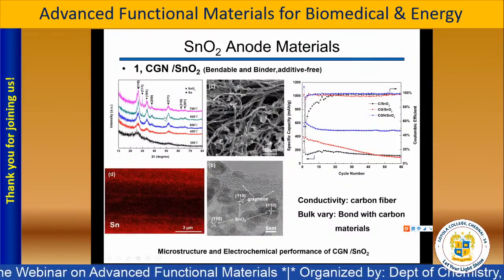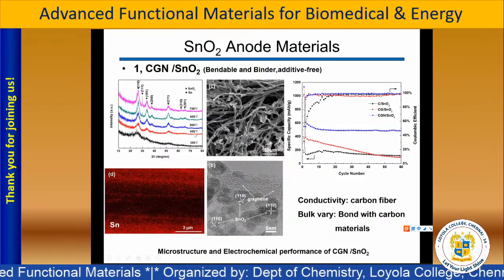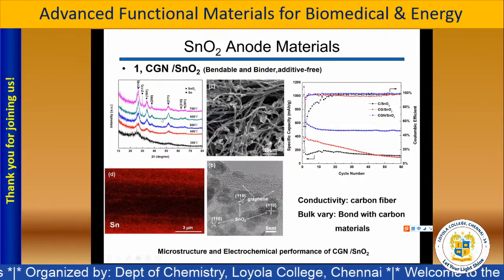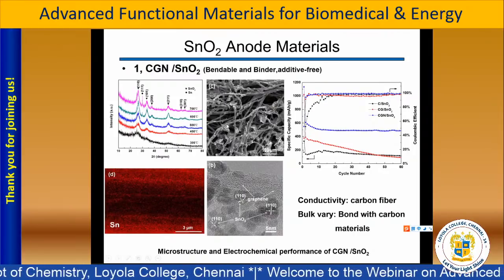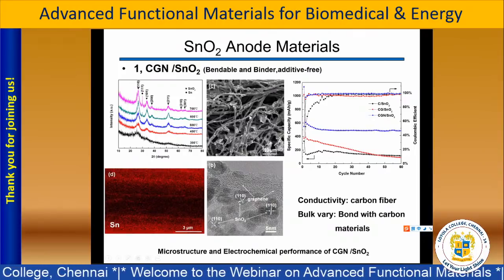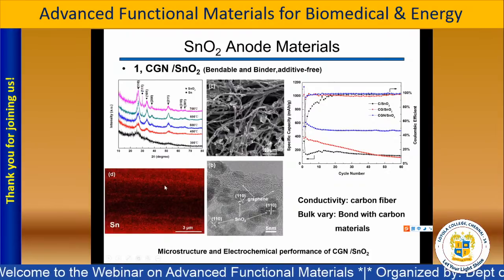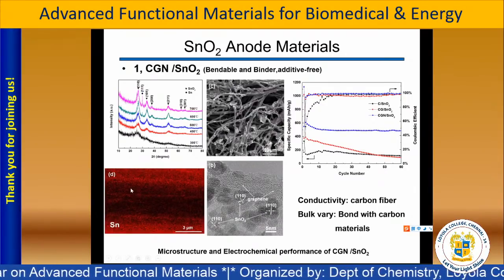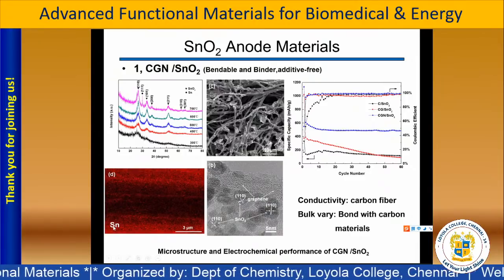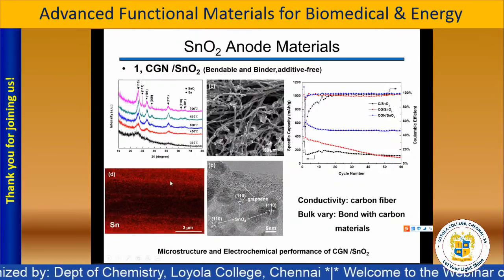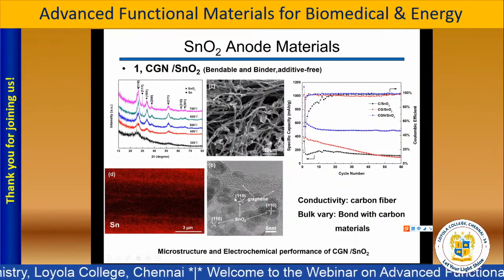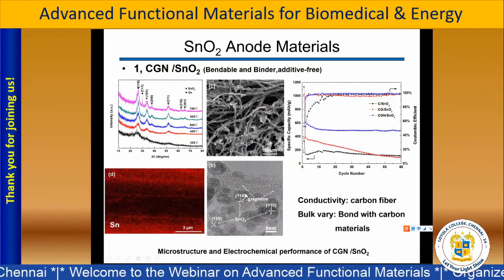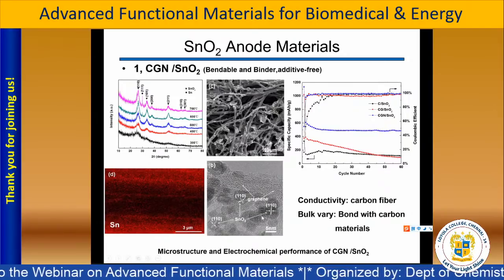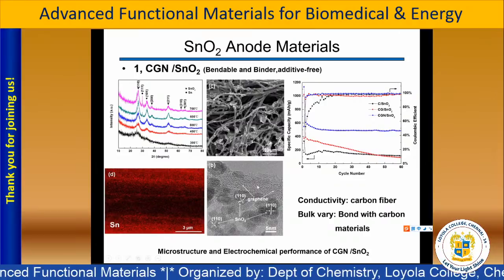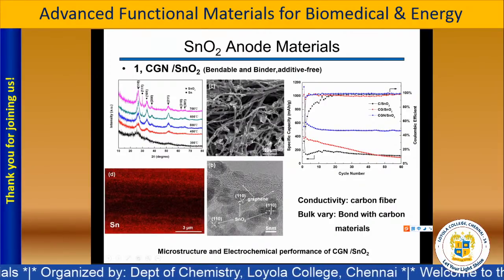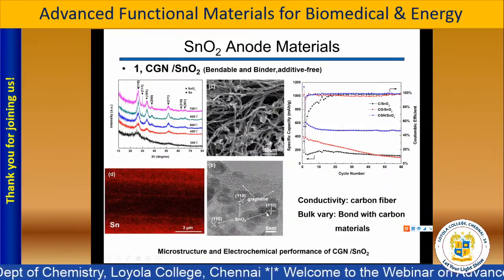After we heat treat this material at different temperatures, we can see that the crystal phases are the same. And from the SEM, we can see that every carbon fiber is covered by the graphene. And the EDS results show that on the surface of the carbon fiber, plenty of tin atoms are homogeneously anchored. And when we take the TEM of the graphene, we can see that small tin oxides are anchored on the graphene surface. And the size of the oxides should be tens of nanometers.